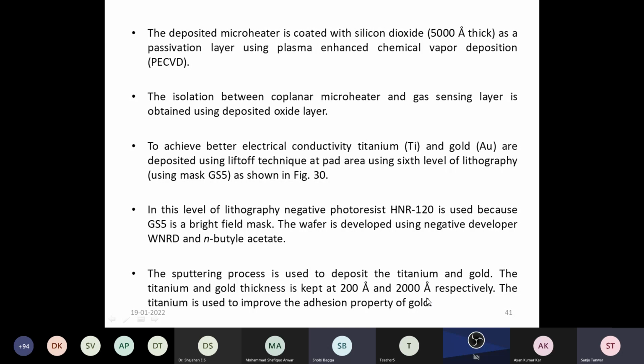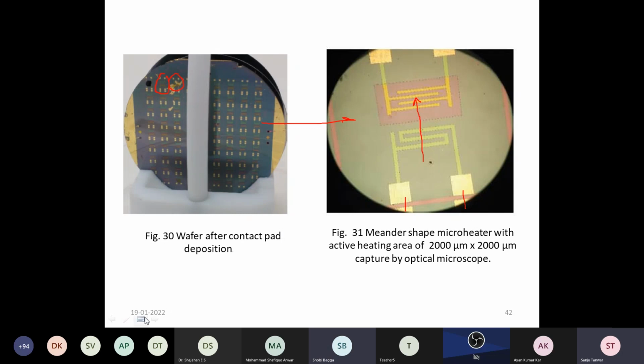Why do we use the titanium? Because titanium is used to improve the adhesion property of the gold. That's why instead of using only gold, we first deposit the titanium and then gold. So these are our gold contacts. These are the gold contacts. While this is my meander shape micro heater.